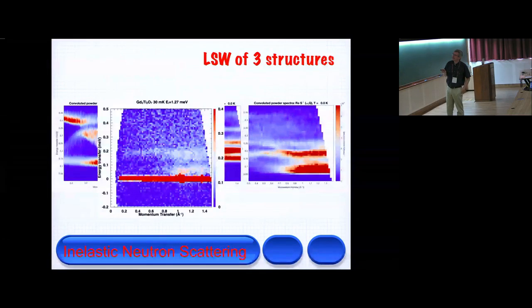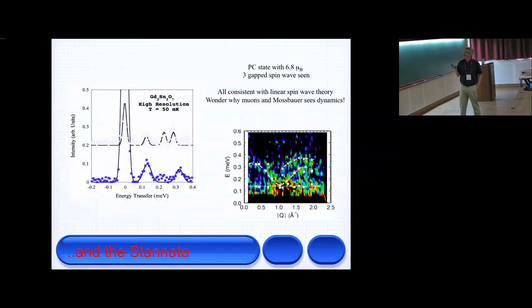And we did that. We can take these data and the models and do line plots through them. But I haven't shown that. An old one that has been published is that stannate. So we take the Palmer-Chalker, and Michel Gingras at Waterloo had done the linear spin waves for Palmer-Chalker. And we took our data and fitted these peaks. The color contour plot doesn't show too much, but the dots in here are where all these peaks are. And then the dashed lines is Michel's theory. So we believe that, we didn't disbelieve it, but the Palmer-Chalker model seems to be appropriate for the stannate.